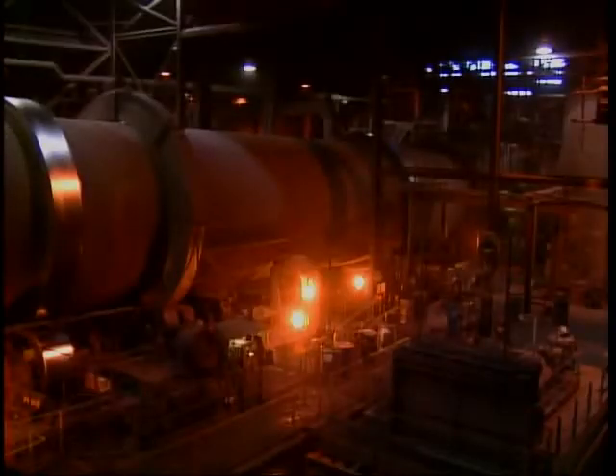The green balls are dried and preheated beginning at about 500 degrees Fahrenheit. As they move along a traveling grate system, temperatures continue to rise until the green balls are fed into a rotary kiln. Fired by either natural gas or coal, the kiln temperatures reach about 2,400 degrees Fahrenheit. This hardens the pellets so they can be shipped and used efficiently in the blast furnaces at North America's steel mills.